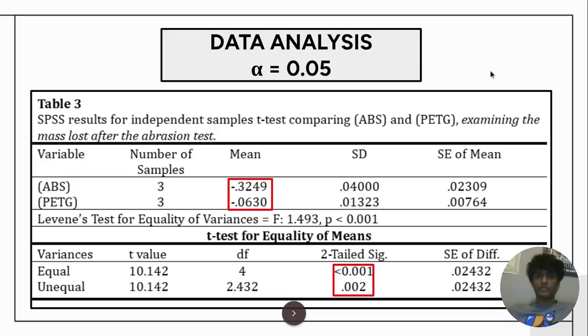In terms of the abrasion test where mass loss was measured, ABS had an average mass loss of negative 0.3249 and PETG had a mass loss of negative 0.0630, and the p-values were below 0.001 and below 0.002, which is again far below the alpha threshold of 0.05, indicating there is a statistical significance between these values, but PETG performed better than ABS did and lost less mass on average.